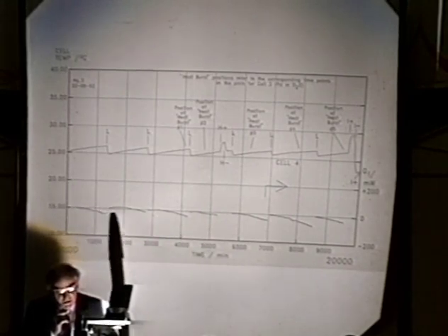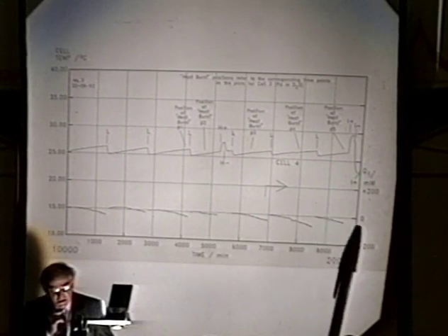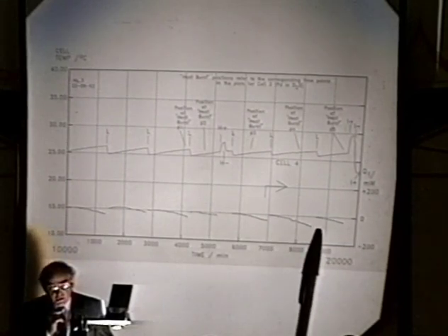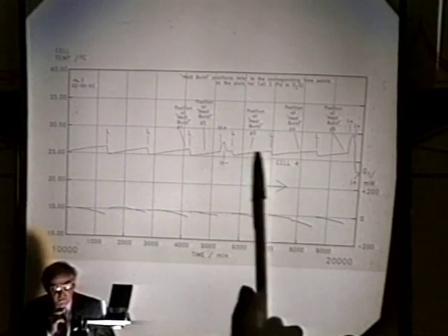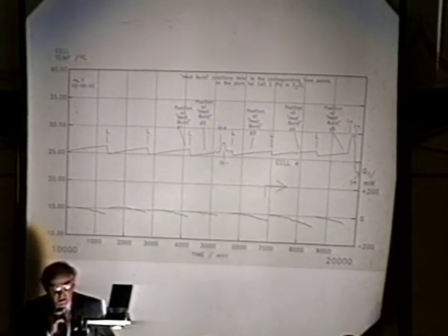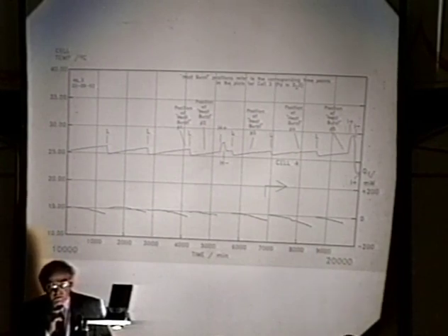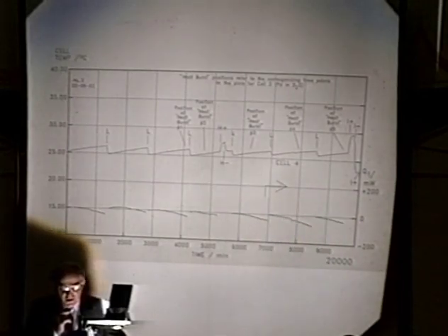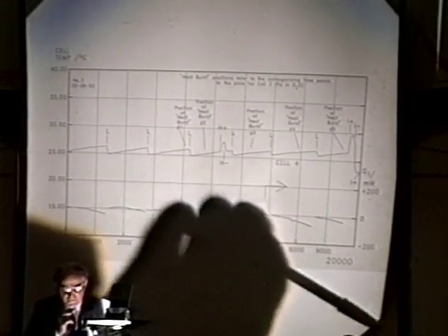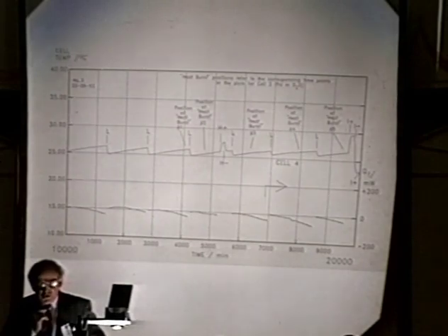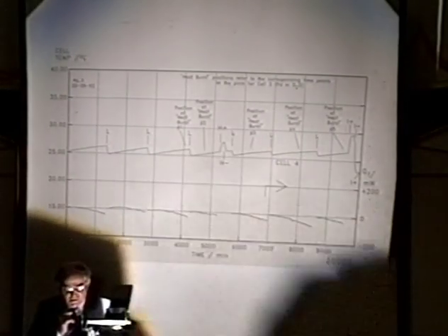And we see that eventually these cells become slightly endothermic, and that means we have overestimated the change of the heat transfer coefficient with time. But that's okay, because we're going to have a look at the D2O cell, and it's better to overestimate. It's better to go on the side of making something negative. If you're looking for an effect which should make something positive, it's better to go on the side of making it negative. So let's just have a look at what happens when we look at the D2O cell.